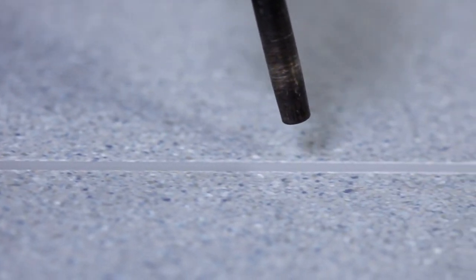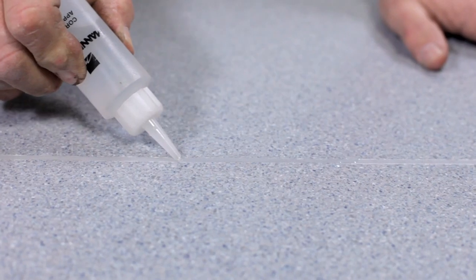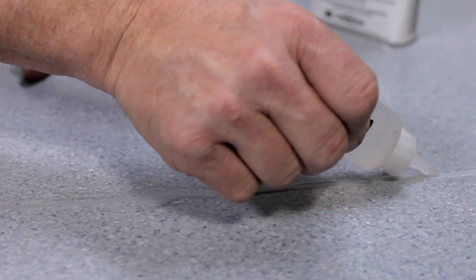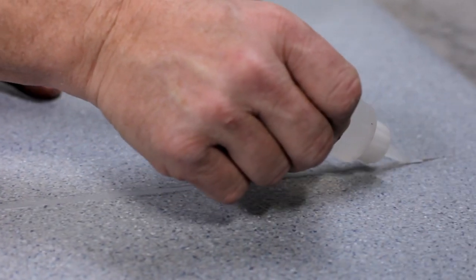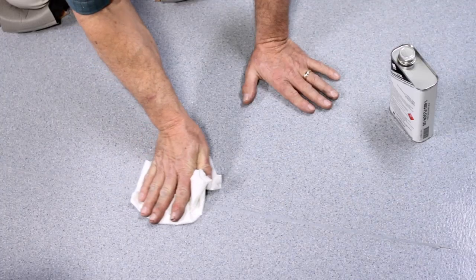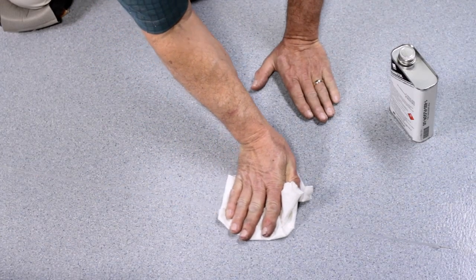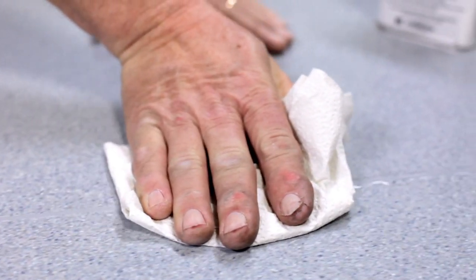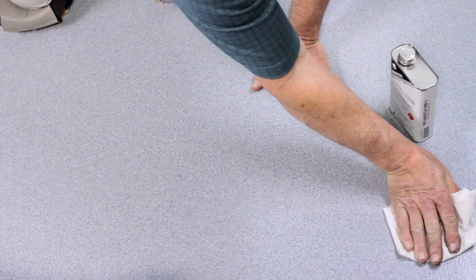The trimmed rod should be heat glazed by directing a flow of hot air from the heat gun over the rod. Chemical glazing can be achieved by applying an application of Mannington Commercial MCS 42 seam sealer over the rod and then wiping with a clean white cloth. Do not wipe off the seam sealer when using camouflage weld rod.